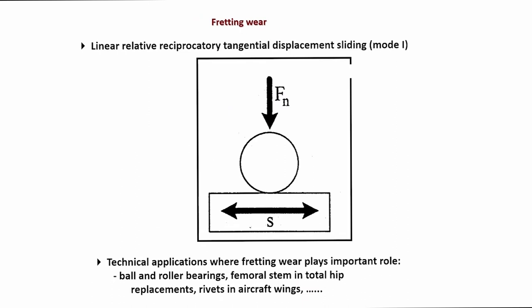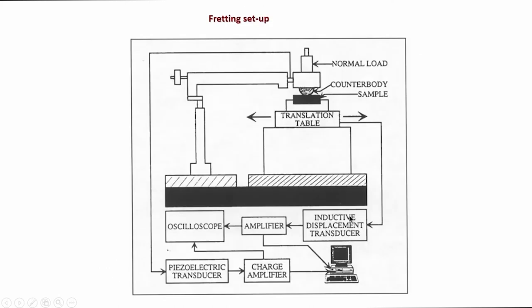Okay. So, like in some of the earlier case studies, we also use the fretting wear of this transformation toughened zirconia ceramics, and this is the fretting wear of mode 1, that is linear, relative, reciprocatory, tangential displacement sliding. So, you apply the load against, this is a typical ball on flat type of configuration where the flat is given a linear reciprocatory sliding of very small amplitude like 80 micron and so on. And this fretting wear has major applications like in ball and roller bearings, femoral stem, in total hip joint replacements and so on and so forth.